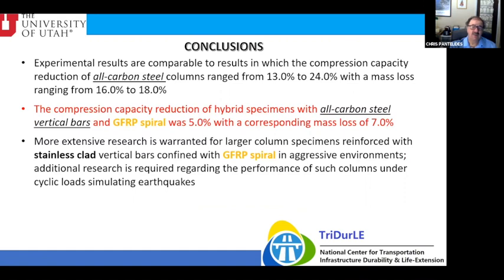So comparing these two studies, the experimental results from the previous study are comparable, where we had compression capacity reduction of the all carbon steel columns ranging from 13 to 24%. You would expect that because even the mass loss ranged from 16 to 18%. But the compression capacity reduction of the hybrid specimens with the all carbon steel vertical bars and the fiberglass spiral was about 5%, and the corresponding mass loss was 7%.